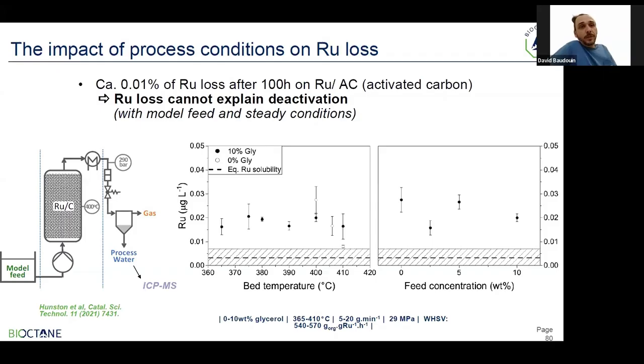And we were able to test the leaching, or loss of metal, from the fixed bed at different conditions, so different temperatures and different feed concentrations, because we know now that feed concentration has a big impact also on leaching of some metals. And we observed that there was no big difference, no effect of these conditions, at least the ones that we applied, on leaching, which remains extremely small. You can see that the units here are micrograms per liter of ruthenium. And this is close to the thermodynamic value calculated and that can be found in literature.